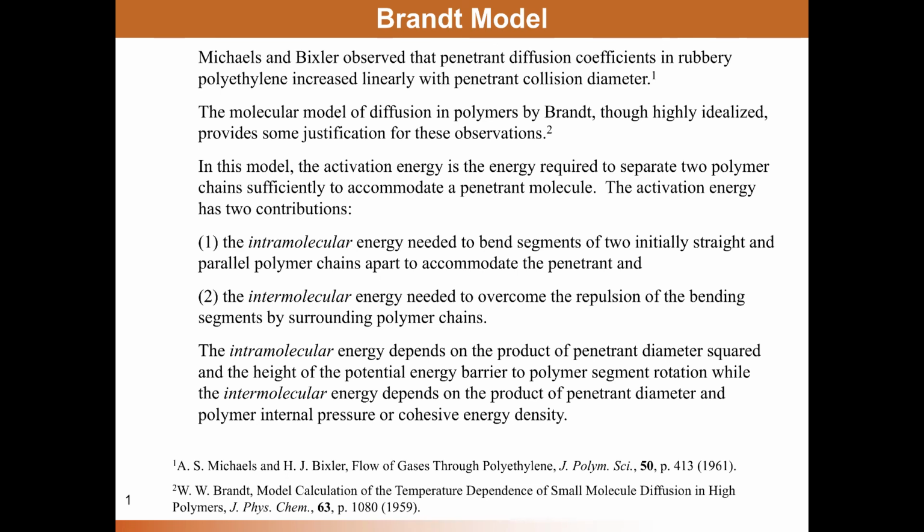There are arguments in some cases that, for example, in rubbery materials like polyethylene, the diffusion coefficients are seen to increase linearly with penetrant diameter, and this is taken to indicate that the dominant contribution to the energy of activation is not this first one that Mears was so concerned about, but it is this second factor that Brandt introduced.